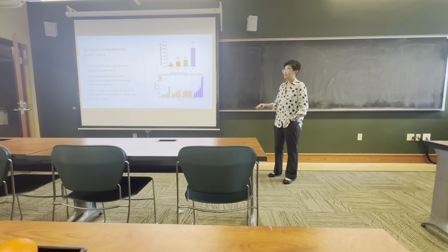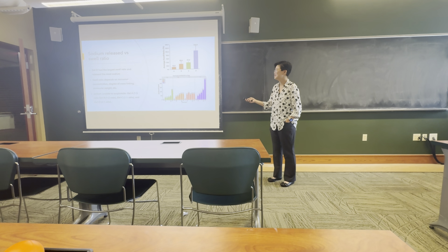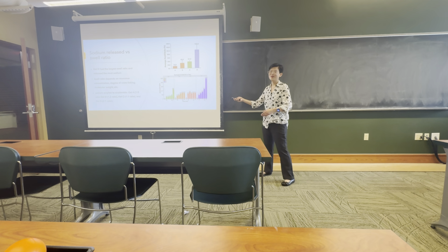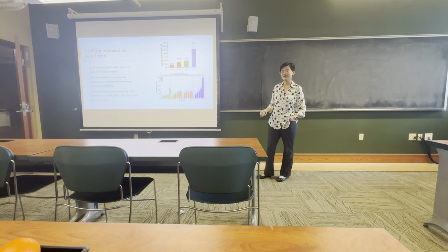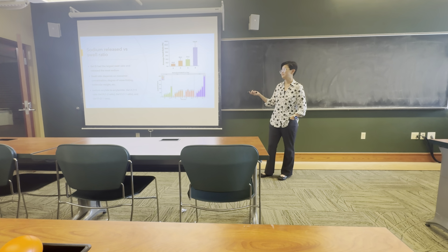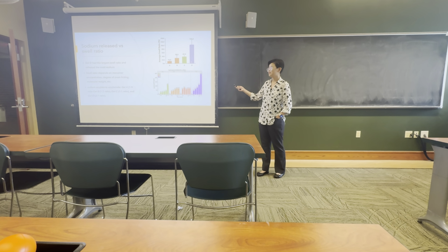Okay. And then, so the gel, like I said before, gel D has the greatest swell ratio. So this is their sodium released over time because one of the monomers in the polymer was sodium acrylate, so it's expected that once it's in solution, it's going to release some sodium and exchange ions for sodium. So D had the greatest swell ratio, released the most sodium.